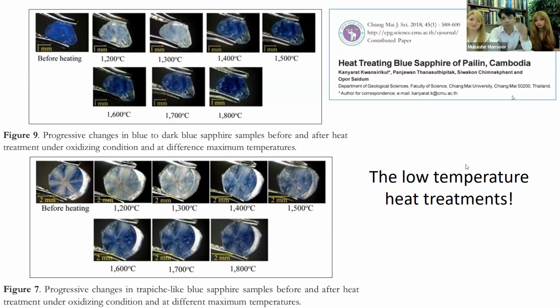And there was this beautiful paper by the Chiang Mai University where they actually showed how the changes in color of a sapphire occurs as you increase your treatment temperature. So even a very dark blue, if you treat it at a rather low temperature, you can get a complete destruction of that blue sometimes. But even for the worst cases where the transformation of the color is not so simple, you always get some lightening of the color. So this has become a very standard procedure in a lot of the sapphires from Australia, from the many basaltic regions, where you have these inky blue colors. You do the treatment at a low temperature, and then for an extended time, and then you get a much lighter color as a result of it.